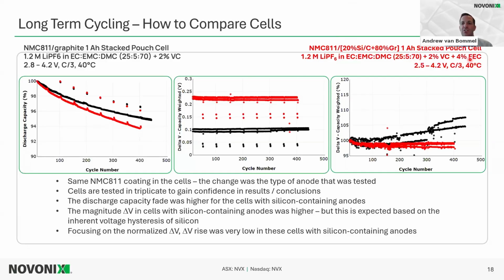There's a little bit of change in the electrolyte and the voltage ranges because it's a silicon-containing anode. But we should focus on the change being that anode that contains silicon. It contains this silicon-carbon material, 20% silicon carbon, 80% synthetic graphite in the anode. Again, these are 1 amp-hour stacked pouch cells, and these are done in triplicate. We might be seeing just two tests here, but there are overlaps. We usually do triplicate to gain confidence in the results and conclusions.